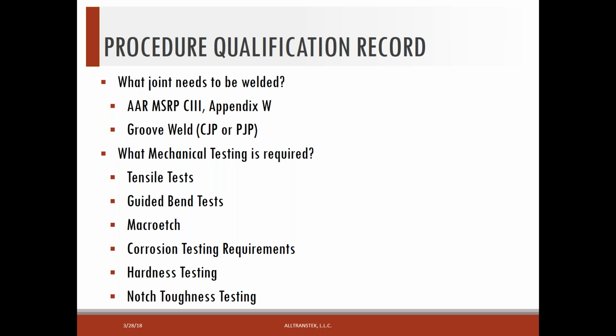The way that we'll establish that is with a macro etch, and look at the cross section of the weld and make sure that we have at least whatever specified amount of penetration is required. Corrosion testing is required if we have corrosive commodities to be hauled in a tank car tank, or if we're exposing a valve to a corrosive commodity, or a siphon pipe, or anything, thermometer well, magnetic gauging device. Any weld there would have to be corrosion tested.